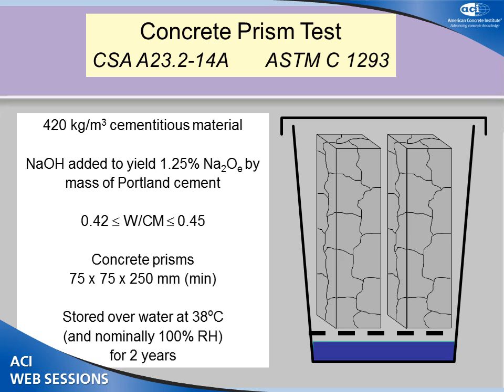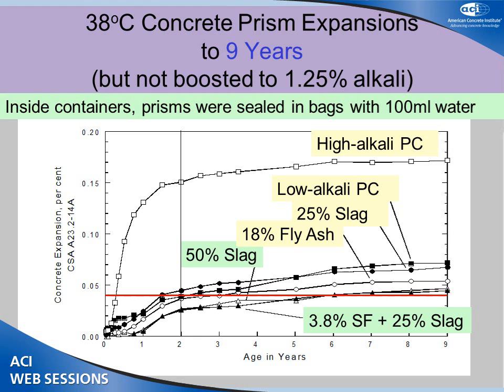The concrete prism test, which is 1293 or the Canadian equivalent, pretty much the same thing. But in this case, we used the cement content of the mix that was 415. We didn't add alkali because we cast these beams from the same mixes out of the truck. So unlike the standard test, we didn't boost the alkalis. So this is what happened.